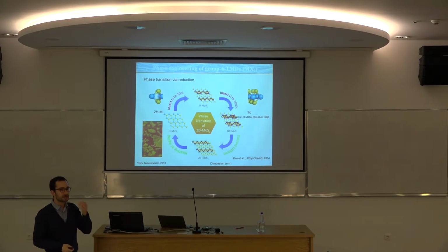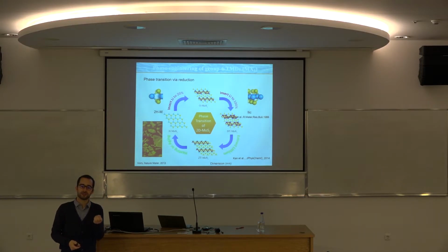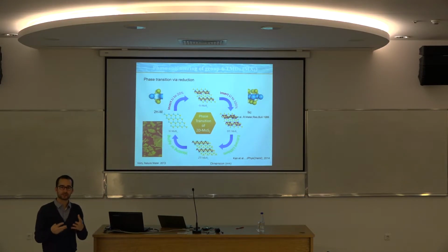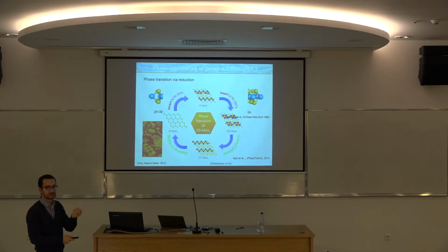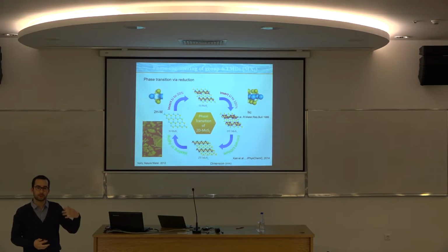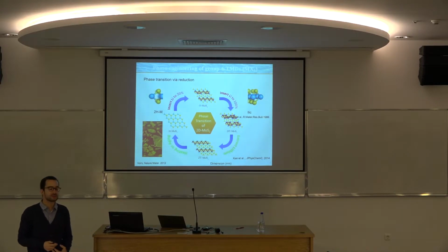So typically this is what happens when you mix your intercalated MoS2 powder with water. Some of the charges will react with water. It's going to give you some hydrogen bubbles you will see in the solution. As a consequence, some of the charge is removed from the nanosheets, and the material will adopt this zigzag chain. Here they call it ZT. So it's still a distorted 1T phase.